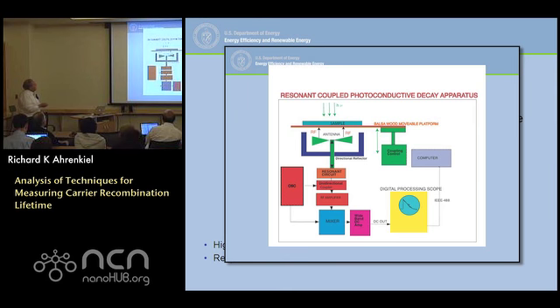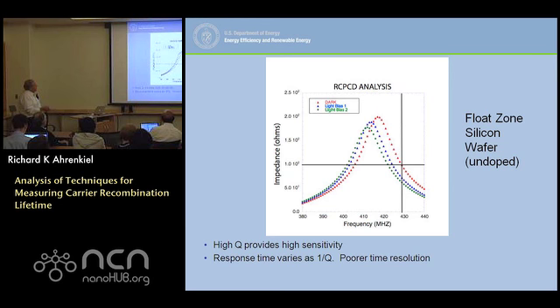Let me do this. So the sample is coupled to the resonance system here. It changes the resonant frequency depending on its conductivity. I'm glad you brought that up because that's quite important. Without a sample there, we would get a very steep curve peaking at some frequency. Now we bring the sample, and it becomes a component in this LCR circuit, a conductive component, and the conductivity lowers the Q and lowers the frequency. So the conductivity of the sample changes the characteristic, which I'll now show here. Without the sample there, we would get a sharp spike somewhere around 430. But when the sample is brought into position, it couples to this tuned circuit, changes the resonant frequency and the Q, and we change the coupling via the spacer so that we get a Q in the neighborhood of 40 or so, which is what we have here.